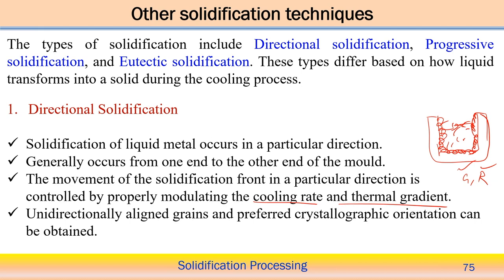Therefore, if directional solidification is achieved, it has a specific advantage: unidirectionally aligned grains, where all grains are aligned in one particular direction. Along with some preferred direction, a crystallographic orientation can also be obtained in the directional solidification technique. So, it is of definite specific interest. If we put some kind of directional properties on a preferred direction, allowing aligned grains along the preferred crystallographic orientation in the direction in which the solidification front moves, then we achieve this objective and directional solidification occurs.